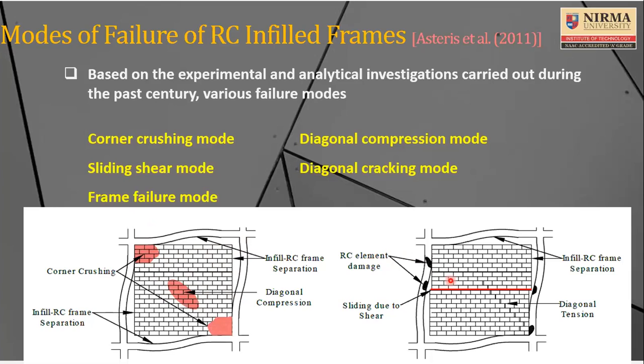And many a time, depending upon the aspect ratio and the integrity between the reinforced concrete frame and the masonry infill, they are also likely to undergo shear. So the joint will completely fail because the shear stresses become larger than the strength of the joint, because of the cohesive nature of the infill with the reinforced concrete frame, and therefore you will find there is sliding also. And because of the sliding, the entire horizontal joint between the two layers of brick also fails. And many a time, because of the relative motion between the frame and the infill, vertical sliding is also observed in experimental investigation.